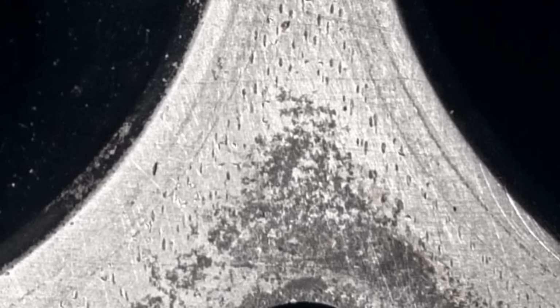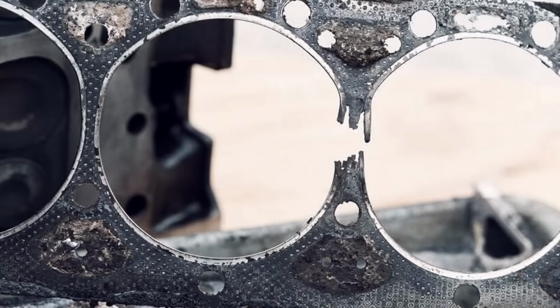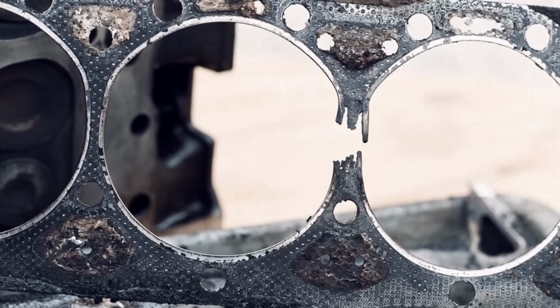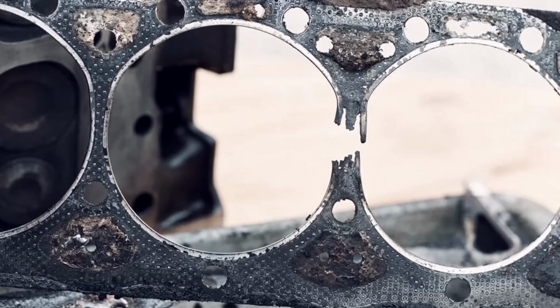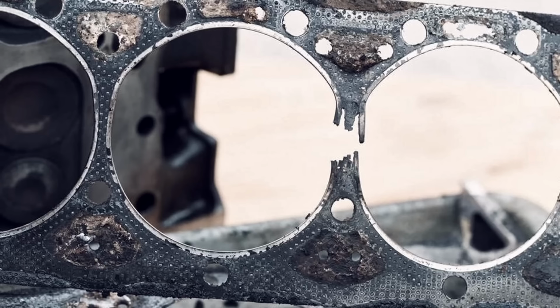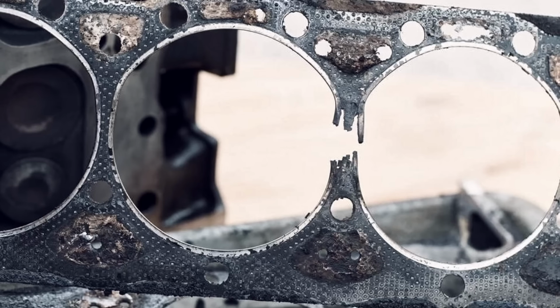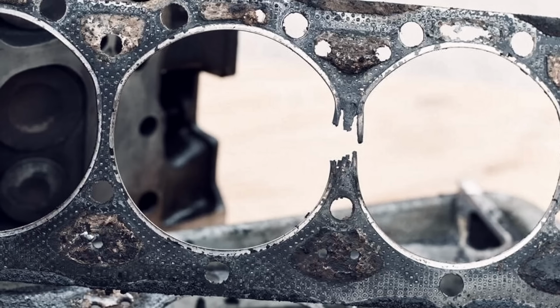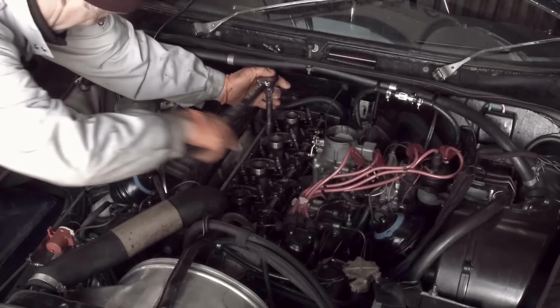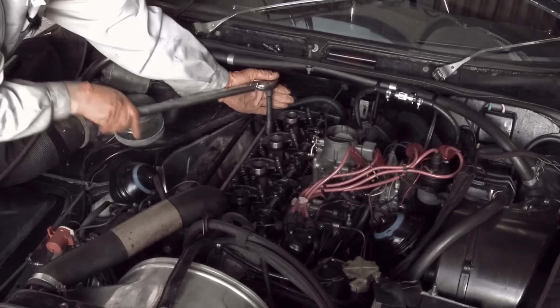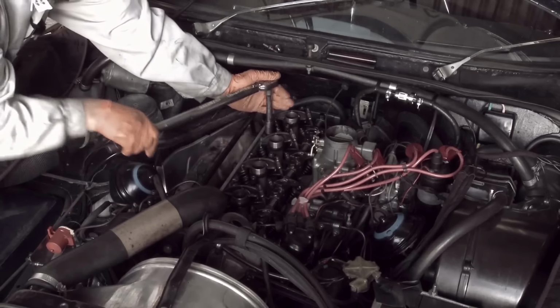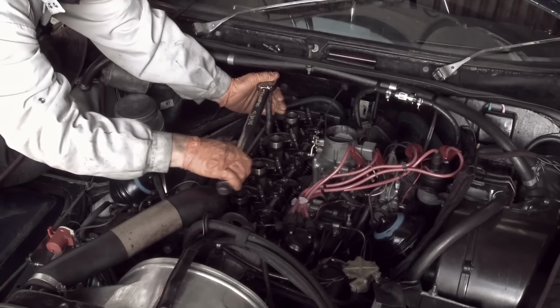Because of its reliance on its surface coating for sealing, composite gaskets are easily compromised by being pressed into dirt or foreign objects. They also rapidly degrade when exposed to abnormal engine conditions, with the two most common modes of failure being composite swell from the steam of overheating and combustion seal failure from both overheating and detonation. Much like copper-clad gaskets, the compressibility of a composite head gasket is carefully matched to its application and the clamping force of the head bolts.